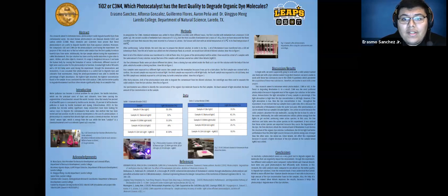If light absorption is high, then dye concentration is still high. However, if it's low, then dye concentration is low. Throughout the experiment, rhodamine B had a pink color when mixed with water. After photocatalysis, our samples became lighter because the solid catalyst had attacked the dye molecule, causing it to lose its color in water.